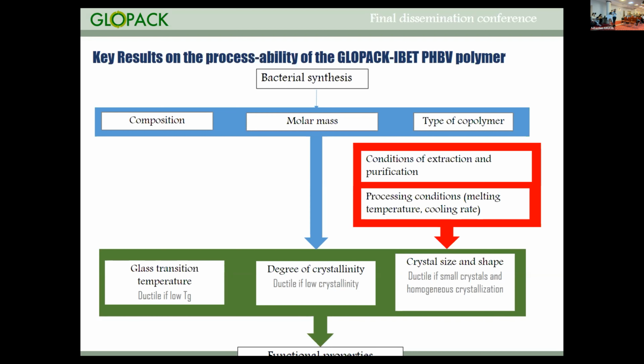These three parameters are governed by the composition, so the HV content, the molar mass, and the type of copolymers: block, alternating, and random. And the parameters in blue can be controlled by the conditions of bacterial synthesis. But what you should keep in mind is that you also have a red box with external conditions, such as the conditions of extraction and purification, and also the processing conditions that can have a strong impact on this green parameter. So even if you control the bacterial synthesis very well, you can completely destroy what was done perfectly if you don't choose the right conditions of extraction and purification, and also the processing conditions. And it's quite typical of PHBV polymers.